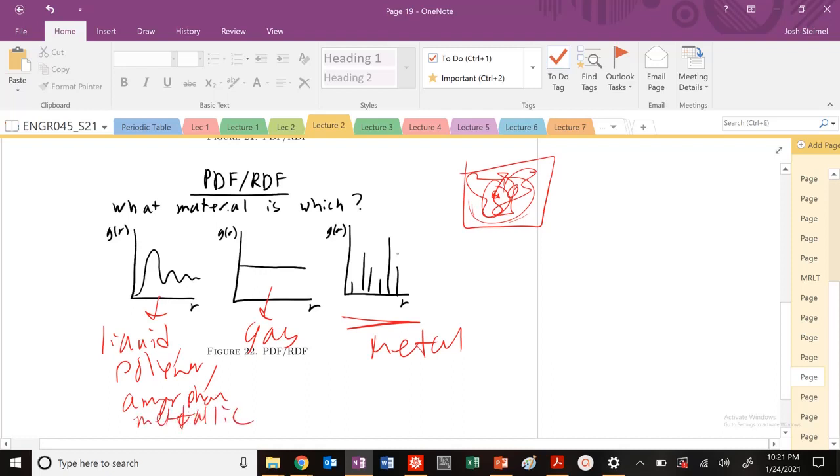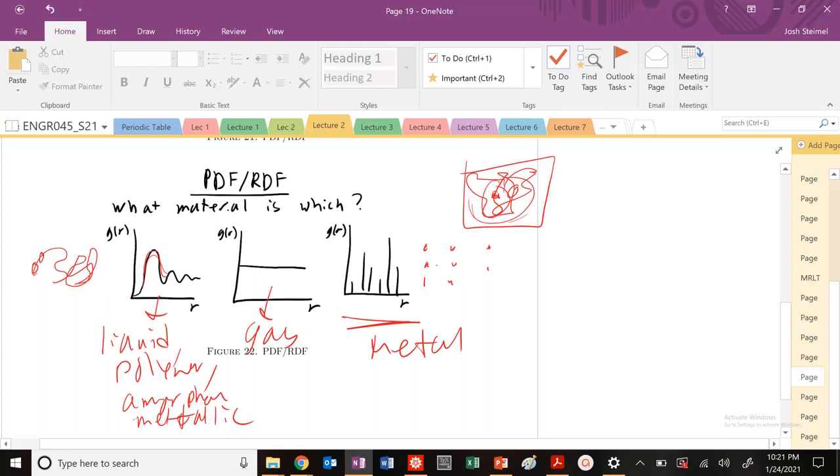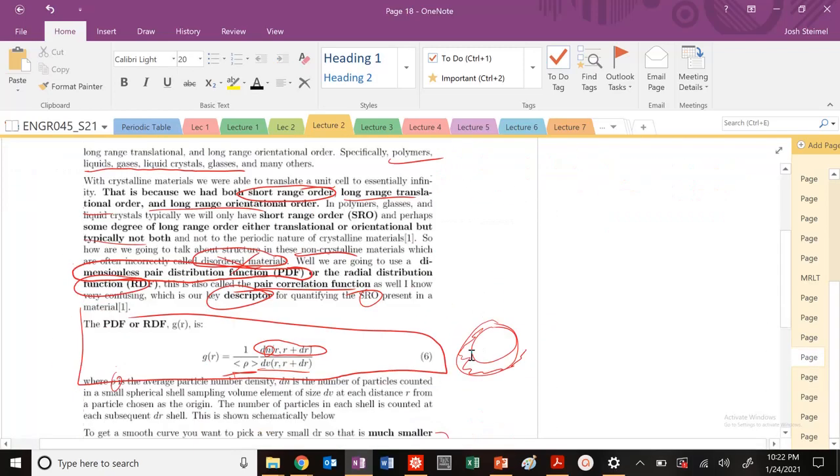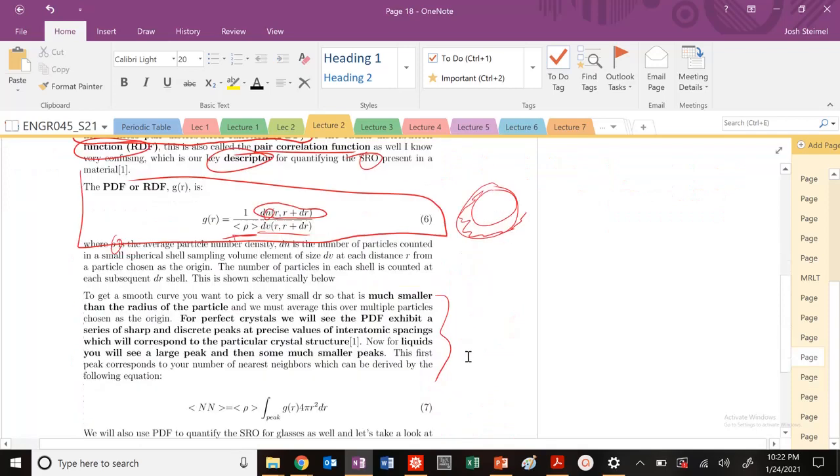So, when we're looking at these peaks, the intensities don't matter as much at this point. But, why are the peaks wider here? Well, it's because here we have this perfect lattice. We're either getting a signal or we're getting nothing. But this is more broad because, for a polymer, it's kind of more like spaghetti, right? I know where each of these monomer units are going to be, but then I don't necessarily know where that's going to be. So, when you average over, these peaks widen. So, if the peaks are wider, that indicates less long-range orientational translational order. But the number of these peaks, if I have more numbers of peaks and for longer distances, that means I have increased long-range orientational order or translational order as well. So, that's the key point when you're analyzing these PDFs and RDFs.